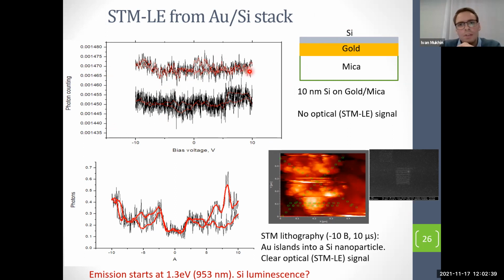We don't have any optical signals. So silicon is not good for that application. But if you applied STM lithography, what is that? You have tunnel contact and you applied 10 volts for several microseconds. You have extremely high local current, which modifies the properties of your layer, and you can produce some morphology features, actually the alloy of silicon material and gold material.